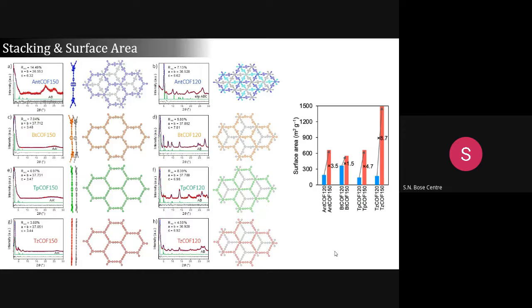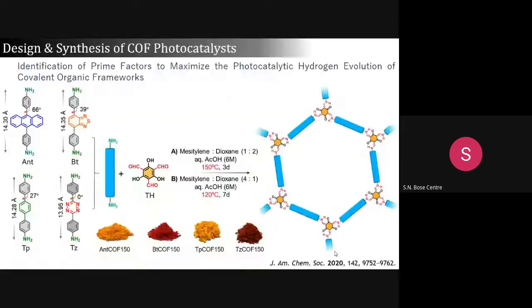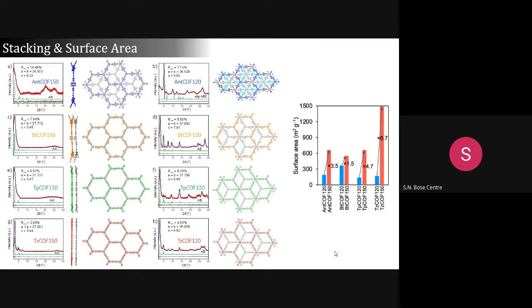Now we tried to understand their structure. If we synthesize this material at 150 degrees, we get one product. If we synthesize at 120 degrees, we get a different product. That we understood from the PXRD pattern. So here you can see the anthracene-based COF, when we synthesized at 150 degrees, the peak is broad like this, whereas at 120 degrees it is quite sharp. If we compare this XRD with the simulated model, we can see this is the AB packing, this is ABC packing. AB packing is nothing but when this is AA packing, this is AB packing, and if the third layer is in a different way, then we call it ABC packing.